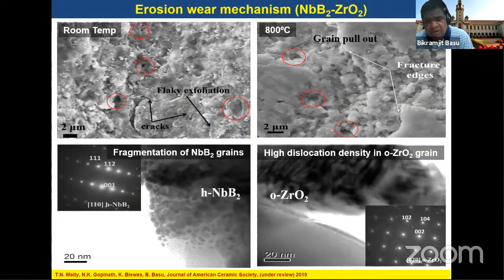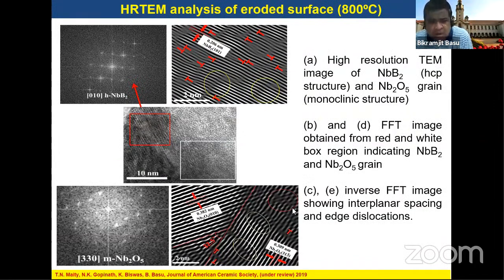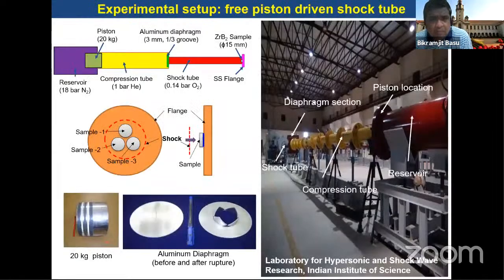Now, when we investigated the as eroded surfaces, we observed a couple of interesting things. One is grain pullout and flaky exfoliation, and apart from this, instead of tetragonal zirconia, we have found orthorhombic zirconia present on the as eroded surface. We went ahead and further found out how Nb2O5 also forms because of the oxidation during the erosion, and what the dislocation activity is on the as eroded surface. We have found that after 800 degrees Celsius temperature testing, there is significant dislocation activity on the as eroded surface. That is very clear from that HRTEM image.